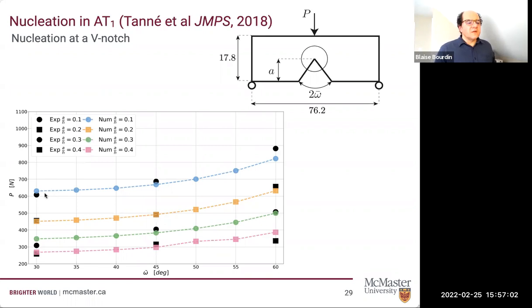The color dots are numerical simulations. And again, we have no parameter we can fudge with. The 3 parameters that we have are Young's modulus, fracture toughness, and the L parameter. And the L parameter, we obtained it from the tensile strength. There's nothing free left. So we just plug that in, we run our computation, and you see that we actually match the nucleation load for every single possible configuration.